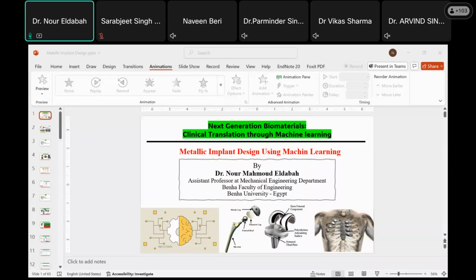First of all is the biocompatibility. You are dealing with the human body, which is very sensitive to foreign metals or foreign substances that enter the human body. In this classification, you will find that some elements are recommended or strongly recommended to be used inside the human body, while others can be accepted at a low concentration, and some others should be avoided. You cannot use them. For example, titanium, zirconium, niobium are strongly recommended to be used. We can accept some amount of aluminium, manganese, iron, and so on. And we should avoid elements like platinum, nickel, cobalt, chrome, vanadium.